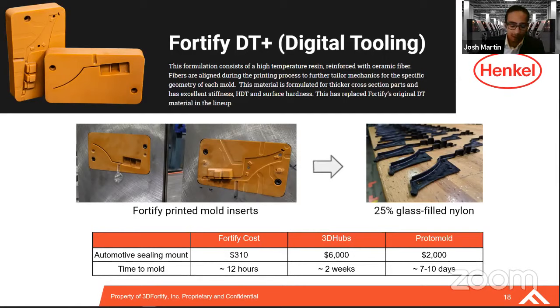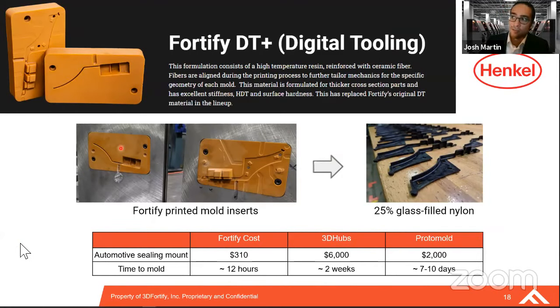And in this case, we've found a lot of traction with injection mold tooling. And so the general concept is that we can reinforce these resins to be tougher, have a higher heat deflection temperature so that they maintain tolerances and leverage the high resolution you get with a light-based 3D printing method. And these materials are able to shoot much more challenging polymers than other additive tooling solutions. And to give you an idea of money and time, we're able to get parts off of this mold essentially 10 times faster at a tenth of the cost compared to generally manufactured, whether it's cut aluminum or steel or other additive solutions here.